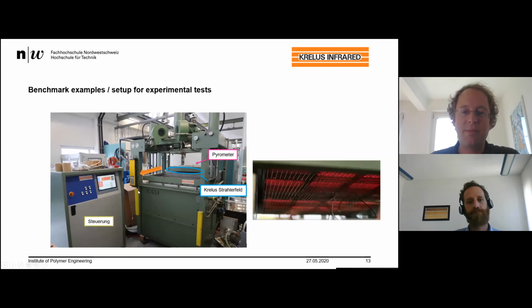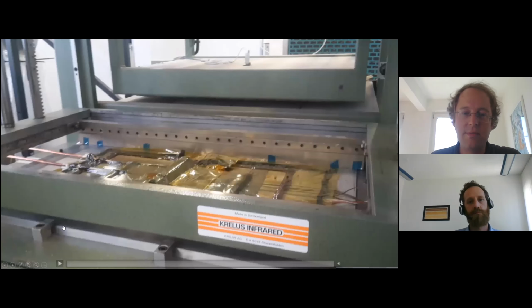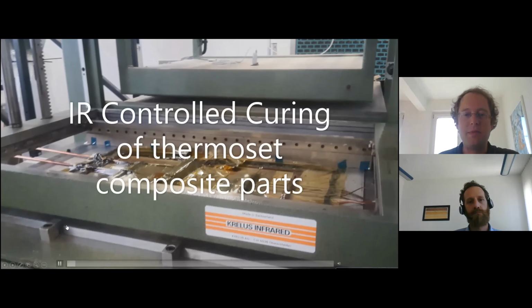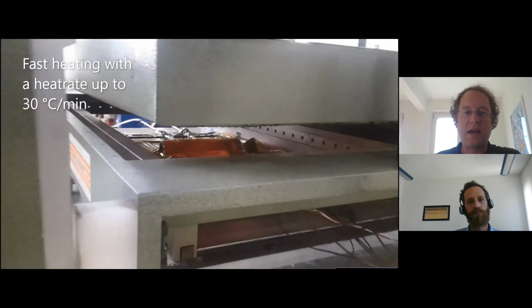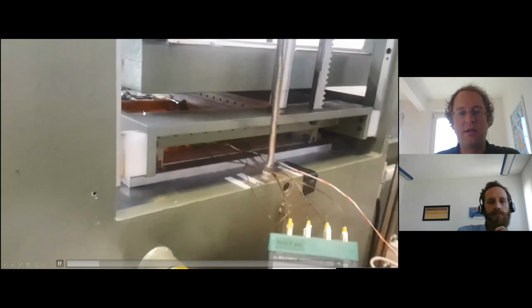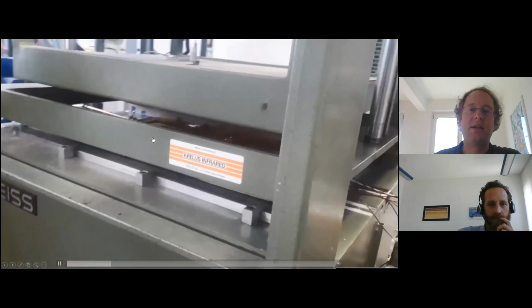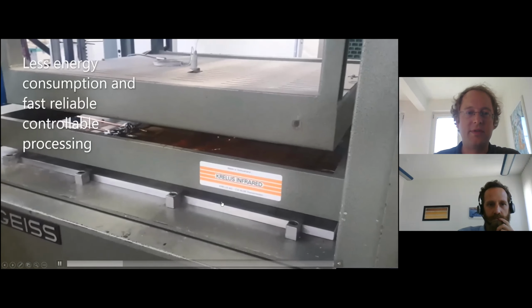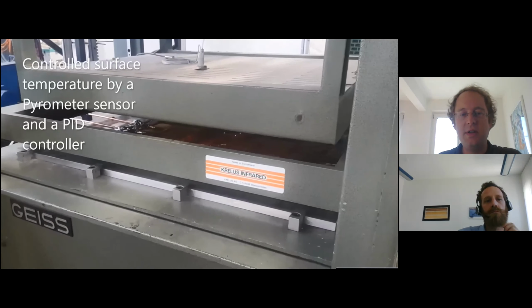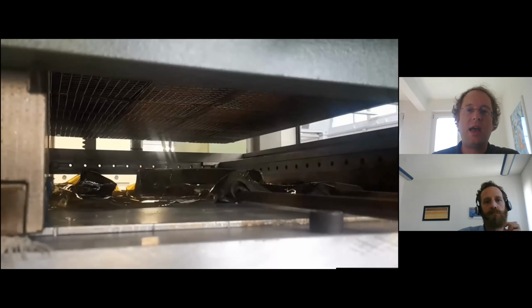So here you can see our setup. So initially, this was a thermoforming machine. And we used the machine different, as I said, for thermoset materials. And here you can see the heat field with some heaters which have different power distribution. So we have a small animation here so that you can see a little bit the process itself. So we have a kind of vacuum setup of this omega-shaped part inside. And we have an open oven, so it's not closed, because we need a certain amount of convection.